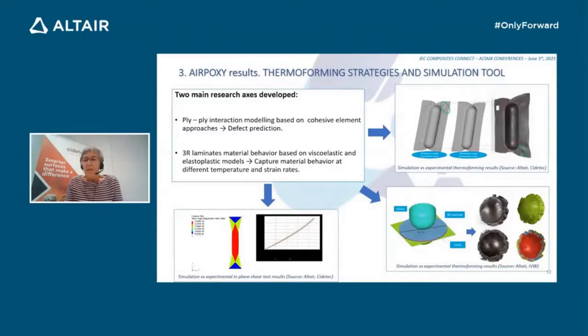For that, 2 different resin models were developed, one considering the resin as a viscoelastic material and the other considering the resin as an elastoplastic material. In both cases, it was confirmed that the models can capture the material behavior at different temperatures and strain rates. The material was calibrated using tensile, bending and in-plane shear tests, and the models were tested on structural scale models such as semi-spherocylinder and hemispherical models that you can see in the pictures. A good agreement with real parts was obtained, and it was possible to predict with accuracy the final shape, type, and location of defects like wrinkles and delaminations.